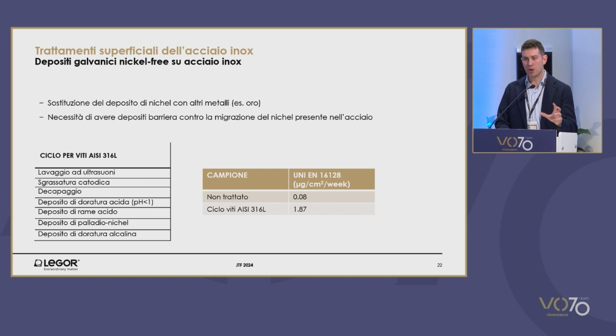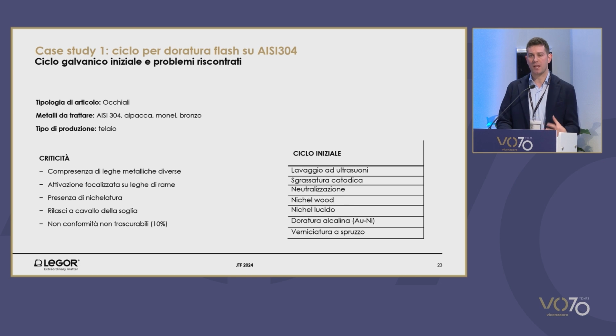This is a project that we've carried out at Legor, where electrodeposition was performed on screws to be used in eyewear using 316L stainless steel. The release is not compatible with the rules. The same screw that was subjected to electrodeposition was releasing nickel 5 times more than included in the regulation. So the barrier was not sufficient.